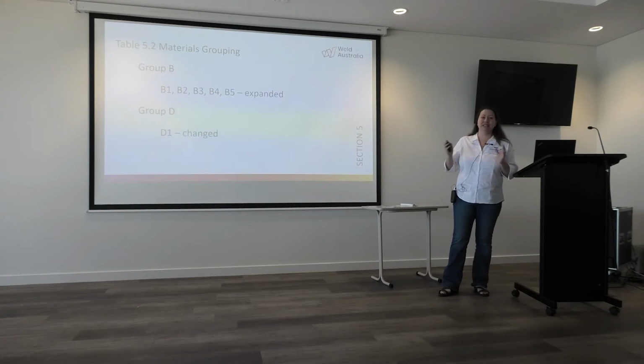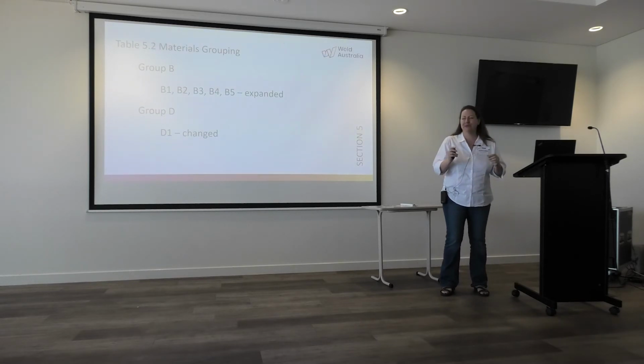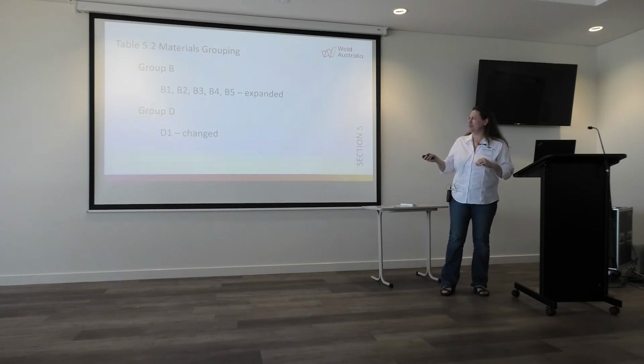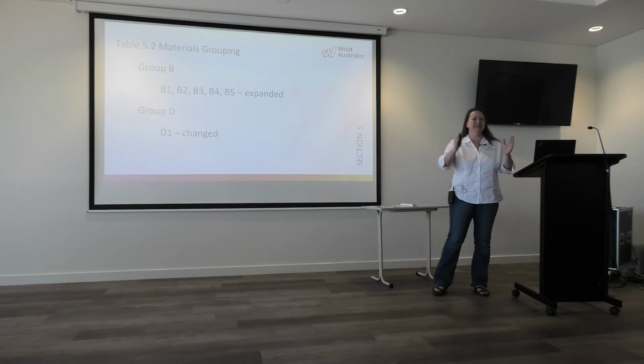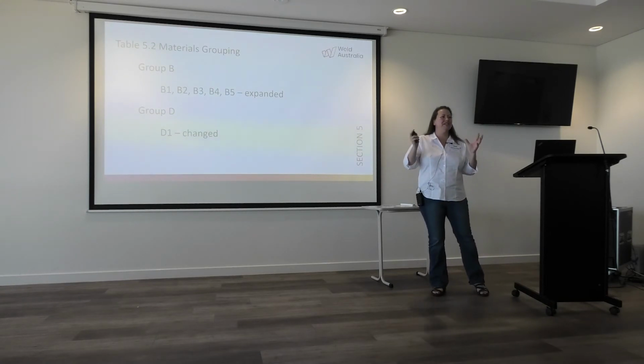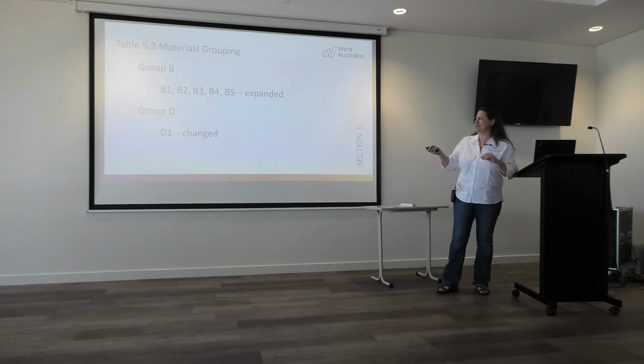And then the D1 is now only one chrome, so the higher chrome molybdenums. And then B4 is what's called WB36. It's a copper, nickel, moly, copper precipitation hardened steel that you use for power stations. B3 is at this point open, and then B2 also, but in B1. So we added in scope to adjust our classification of the standard a bit in terms of materials.